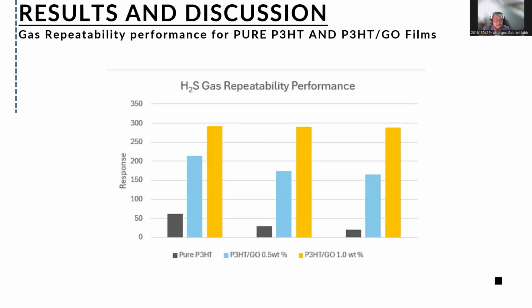Here's the repeatability performance of the pure and P3HT GO films. So pure P3HT has the lowest response in all three cycles. This means that it is less sensitive and less consistent compared with the GO composites. When 0.5 weight percent GO is added to the P3HT, its response improves in all cycles. This is because graphene oxide provides more active sites for gas to stick to, which helps the sensor detect hydrogen sulfide more effectively. So it is a clear step up from pure P3HT.